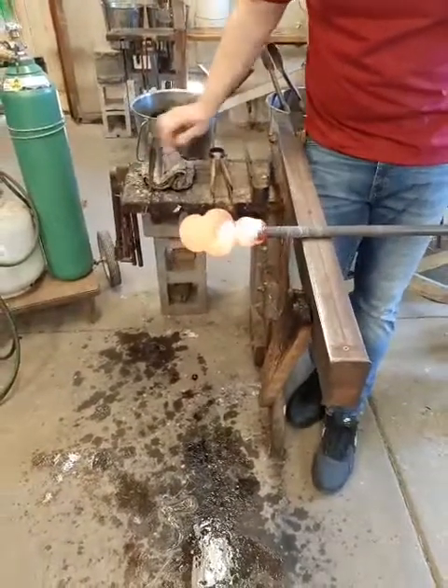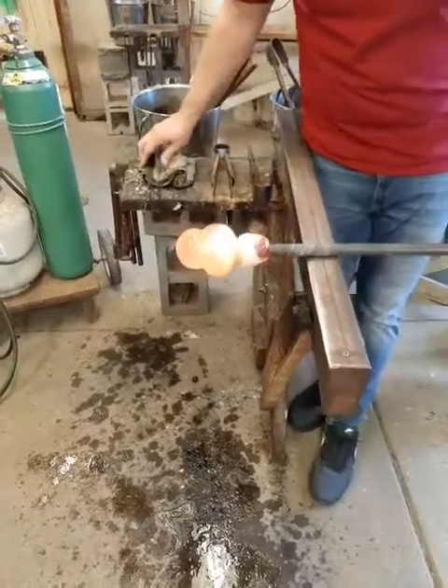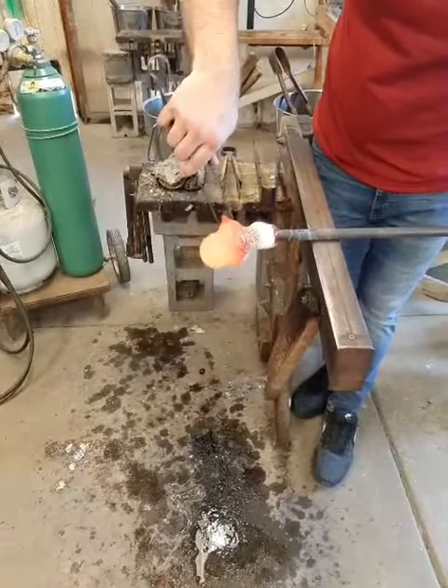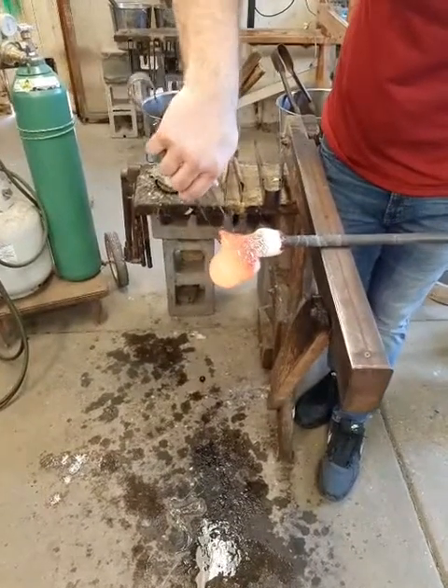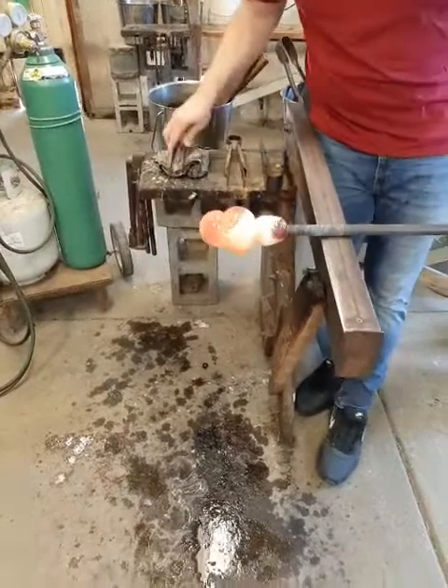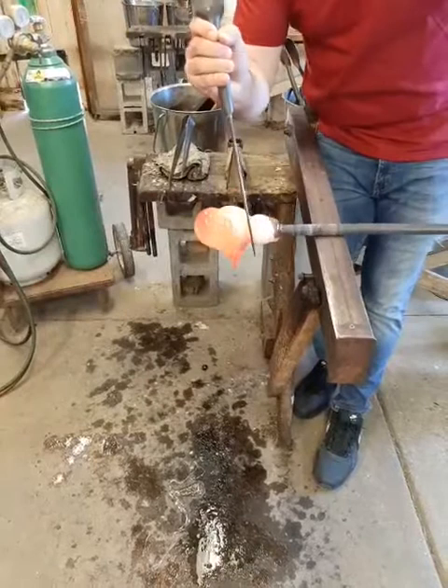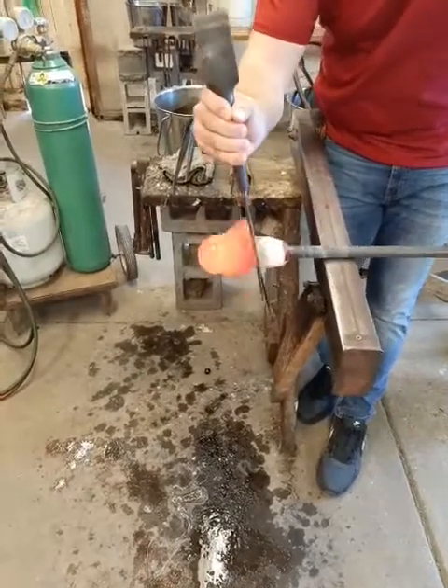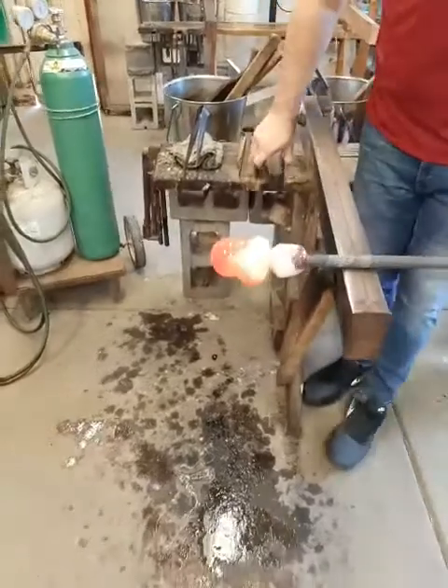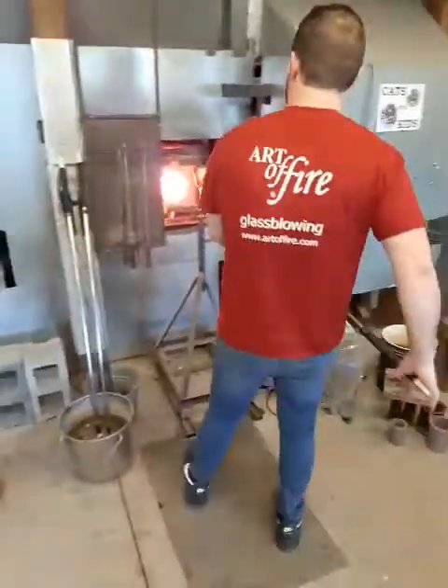Yeah. He'll pinch the backside a little bit. That sounds a little off color, but he's creating the tail right now. Notice that he does this a little bit at a time. He creates a point to reach in and grab. He does not pull the glass a great distance. If he tried to go really far with it, it'd pull out into a really thin string. And he doesn't want that. He wants the broader tail. And by doing it slowly and under control, he manages to keep just that.